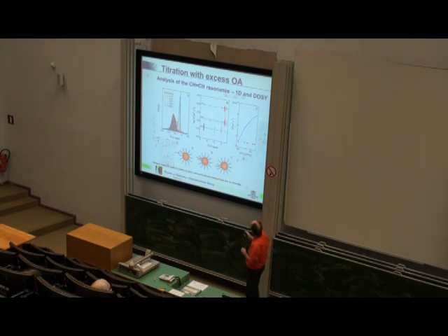We have the original bound ligands. These are in blue. That's the broad resonance. And then the red ligand that we have here, that's the excess. And we have a kind of exchange process where, first of all, the excess can physisorb in this ligand shell. And this is a very fast exchange. And this leads to the additional resonance with a kind of intermediate diffusion coefficient. Why intermediate? Part of the time this ligand is free, part of the time it's in the ligand shell. And the more free ligand you have, the more your results will evolve towards the free values.